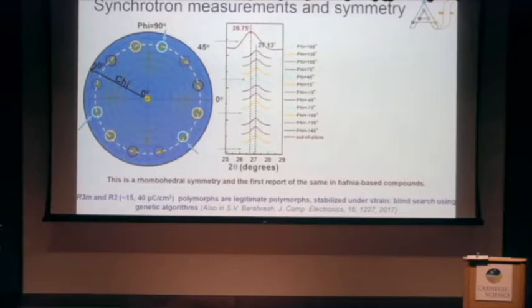To do that, you go to the synchrotron, go back to this pole figure, and analyze, let's say, all these spots, theta-2theta scans around these spots. And here let's concentrate on one particular domain. Here we clearly see that there is a 3-to-1 multiplicity for the 111 peaks. And this is a clear indication that what we have is a rhombohedral phase, which has been reported, but not in the context of ferroelectricity, and which is what excited our theorist, Jorge. So he did find a couple of rhombohedral polymorphs, which can be stabilized under strain using first principles calculations.